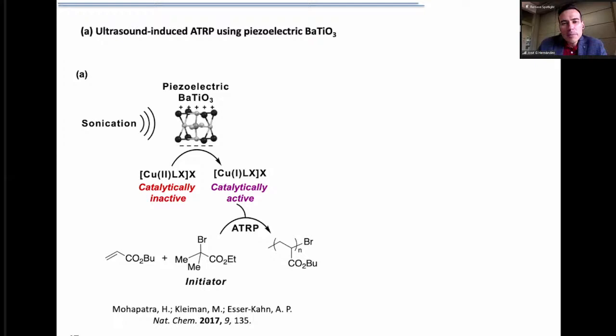For instance, if you consider the presence of a copper 2 complex, which is catalytically inactive in certain reactions, such as an atom transfer radical polymerization, you could harvest those electrons so that the reduction occurs, and then you end up with a copper 1 complex, which is active for this reaction. And this is something that was demonstrated by some colleagues in the US in 2017, so that you could promote mechanochemical reduction by taking advantage of that activity that piezoelectric material has when mechanical force is applied, so that piezoelectric materials were acting somehow as mechanophores for this reaction.